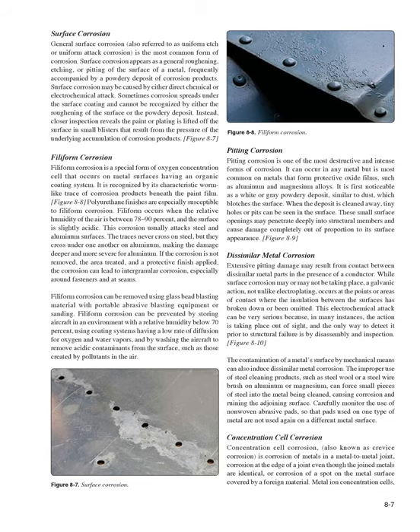Filiform corrosion can be removed using glass bead blasting material with portable abrasive blasting equipment or sanding. Filiform corrosion can be prevented by storing aircraft in an environment with a relative humidity below 70%, using coating systems having a low rate of diffusion for oxygen and water vapors, and by washing the aircraft to remove acidic contaminants from the surface, such as those created by pollutants in the air.